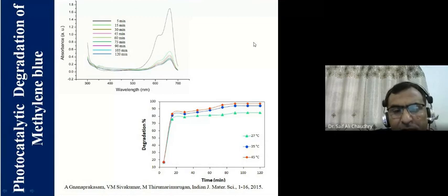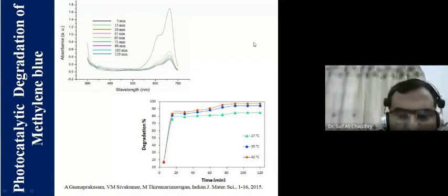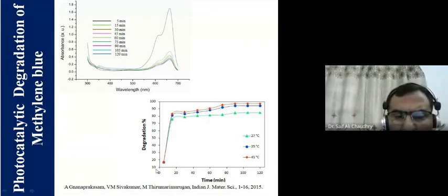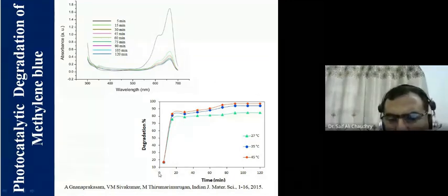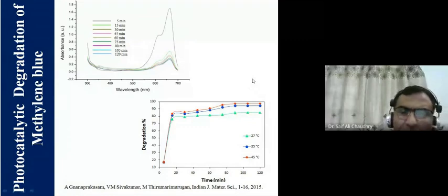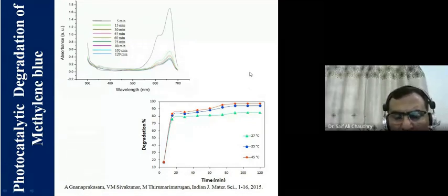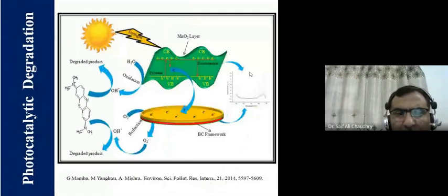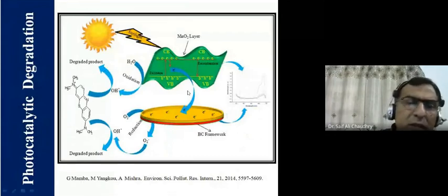Now we have also studied the effect of temperature on the dye photodegradation, and the degradation percentage was higher at 45 degrees Celsius. That may be because the excitation needs more energy, and at higher temperature this much energy is made available.